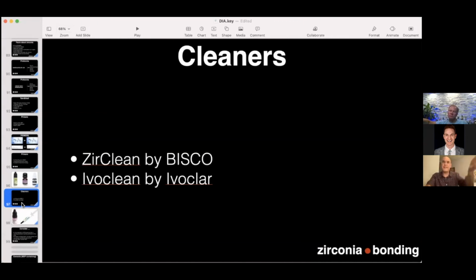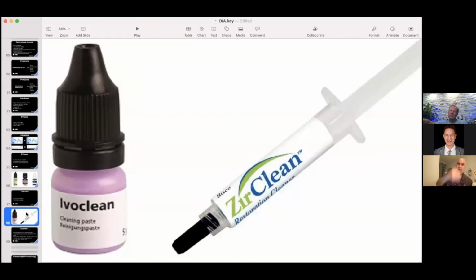I keep telling myself that I have to update these slides. You have Zirclean and you have Ivoclean. Now, I was talking to Dr. Hornbrook prior to the presentation about how these materials work. What they do is that they're super alkaline. Once you have tried in your crown or restoration, whatever it is, and it has been contaminated with saliva, the phosphate lipids in saliva will bond to the bonding sites of zirconia. And you cannot remove that with water.